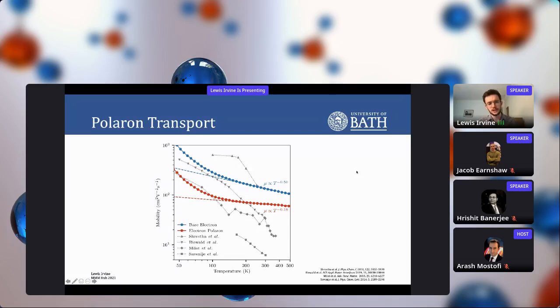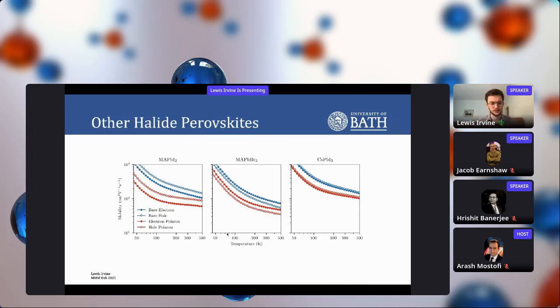But then you also look at the temperature dependence, and comparing with the experimental data in the background, you can see that the temperature dependence is actually shallowed rather than steepened. If our aim is to compare with experiment, this leads us to believe that polaron transport can't be the only thing that is needed to agree with experiment. We did this for other halide perovskites and also holes as well as electrons, just to prove that the overall results of our calculations are fairly general.